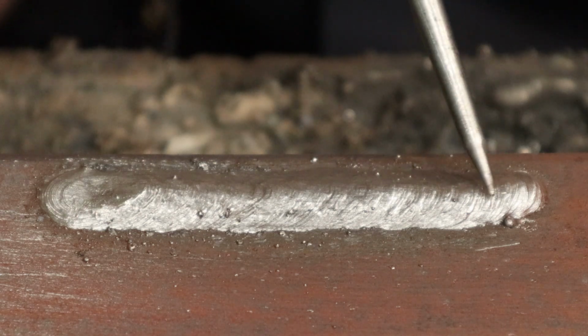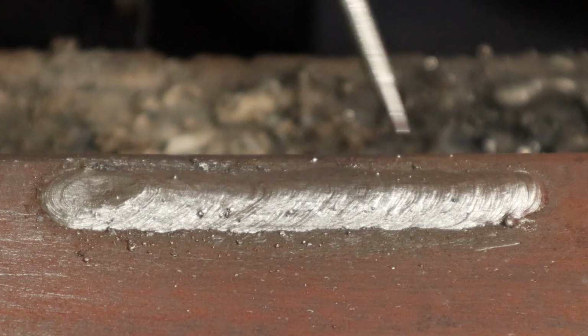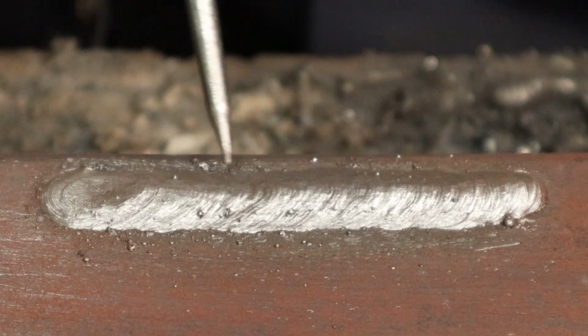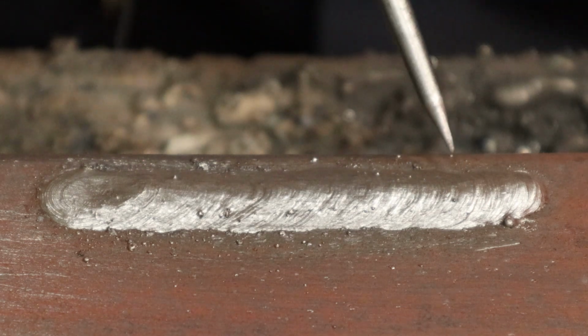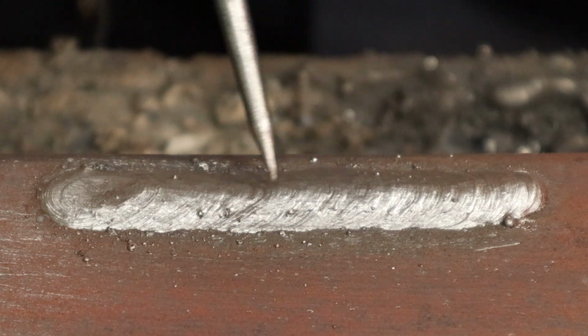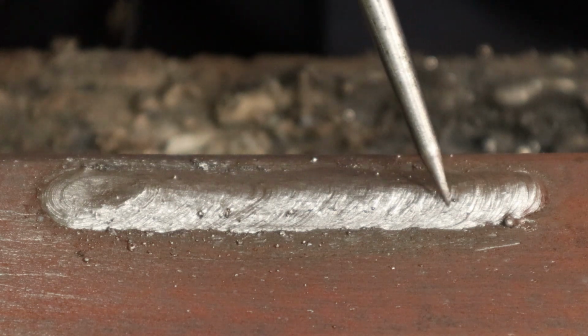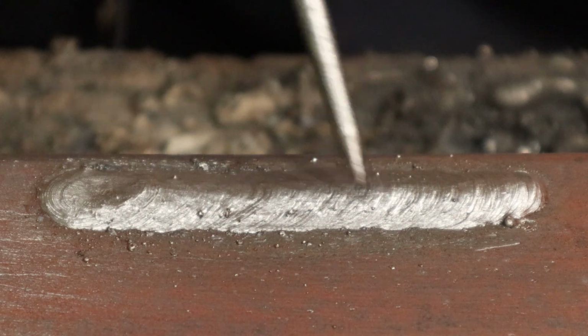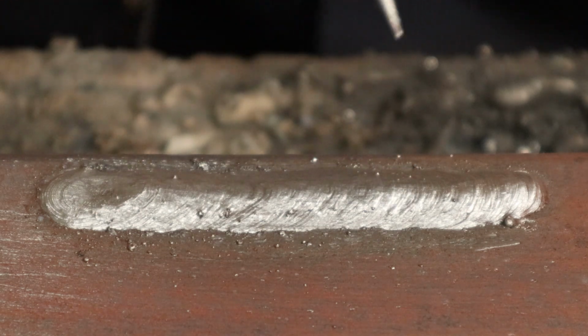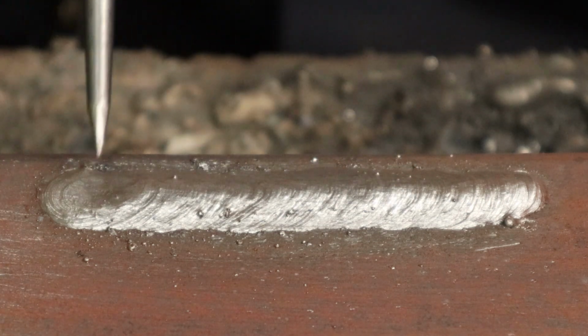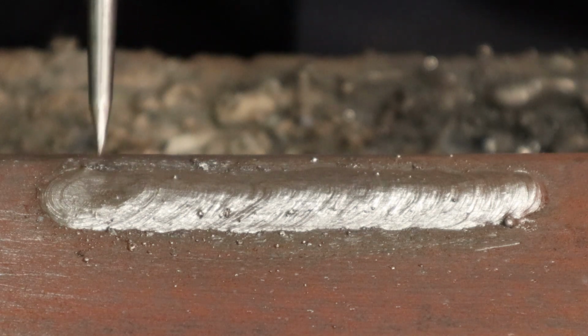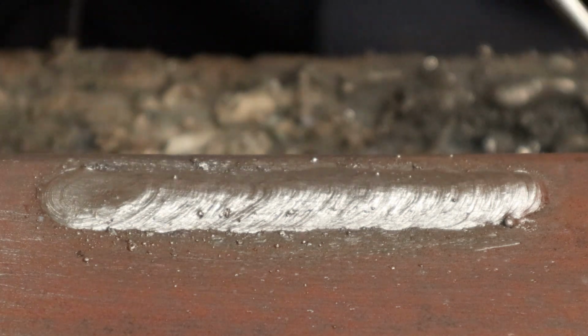The distinct C pattern on the weld bead is there, and the distance between those C's is nice and even. So as I was making the C's, the distance between them is the same. I also have the top and the bottom of the C's as the same, so this doesn't go skinnier or wider. Now, it does go a touch wider at the end, but you can also see that it's because of heat. So you have to remember that we didn't preheat this piece.